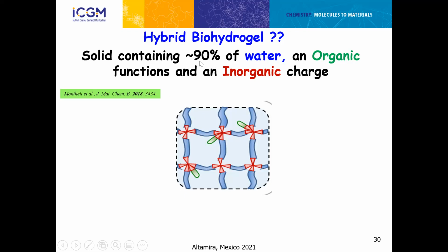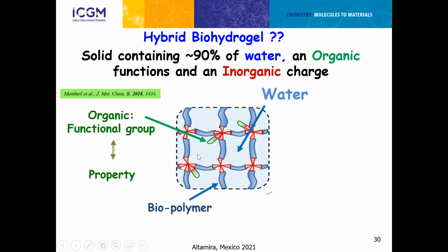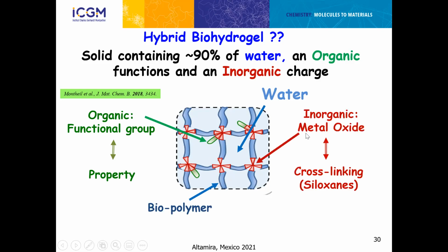Hydrogel is a material containing at least 95% of water, and you have some organic group. I think you suspect that in our case there will be biomolecule, peptide, and of course the cross-linking should take place by introducing of charge here. It's a polymer, but not a simple polymer, silylated, and you have the cross-linking part. So water here, organic group, functional group, the biopolymer, and of course the network.